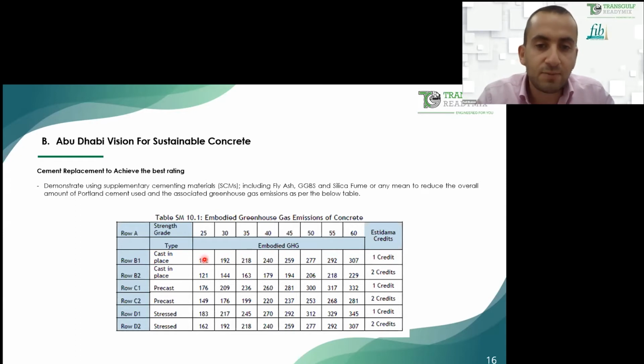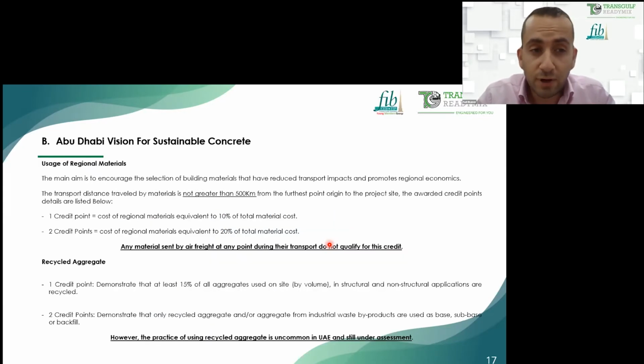To achieve, as an example, for grade 25 MPa, 1 credit, the embodied greenhouse gases generated from this grade must fall below 162 to achieve 1 credit. And if it falls below 121, it will achieve 2 credits. And the same applies for all the other grades. To achieve more credits, Estidama allows the usage of regional material. The main aim is to encourage the selection of building materials that have reduced transport impact and promote the regional economy.